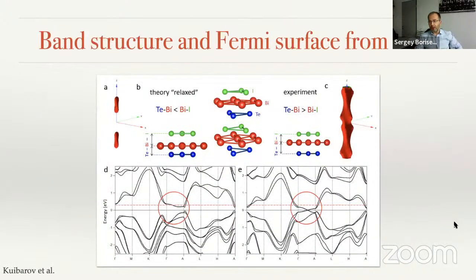We did the calculations ourselves, and when performing this step, we realized that the crystal structure, which is considered nowadays in basically all studies of this material, is based on the relaxed crystal structure, not the experimental one. That is the usual thing when one does DFT calculations: one relaxes the position of the atoms. But in this case, it's very interesting that experiments, not a single one, continuously show that the distance, and the difference is very tiny, between tellurium and bismuth atoms is actually slightly larger than the distance between the bismuth and iodine atoms.